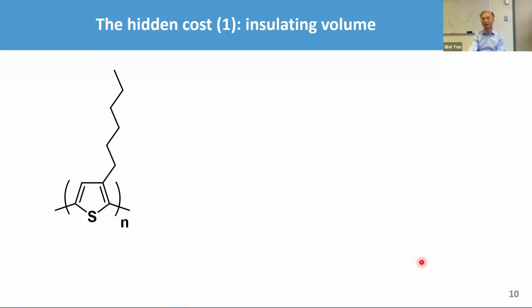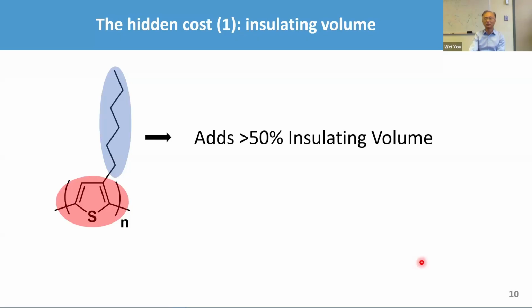All right. But having side chains, honestly, you actually bring quite a bit of hidden cost. So first of all, if you do the calculation, the drawing possibly not illustrating this concept perfectly, you realize that this seemingly very benign, very small amount of hexyl side chains to the so-called poly(3-hexylthiophene) is actually adding about 50% of the volume. And they're insulating, right? Because if you try to make the conjugate polymer conducting, you possibly want to minimize the insulating components as much as you can. Now you essentially suffer from 50% insulating volume, and that's not good news. But we suck it up. We say, okay, we want conjugate polymer to be solution processable, so we need them. So we need to find some ways.